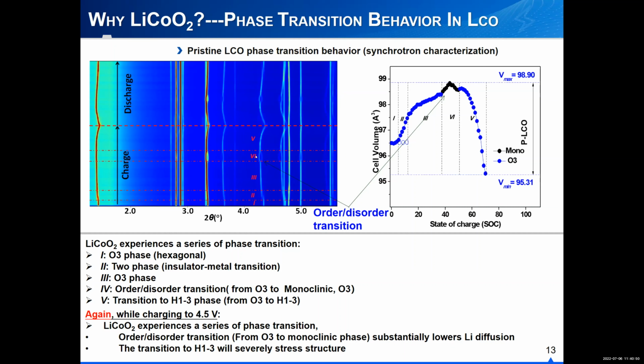Okay, and once again, right here, the number 4 right here, you'll find there'll be the peak split, right? So this phase transition is just the order-disorder transition. That means the lithium cobalt oxide initially has a hexagonal O3 structure, but when it goes to this part, it will be transferred to a monoclinic phase. Once again, the order-disorder transition will substantially lower lithium diffusion, and the transition to the H1-3 phase will seriously stress the structure. We know the problem about lithium cobalt oxide, right? So we have to solve this problem.